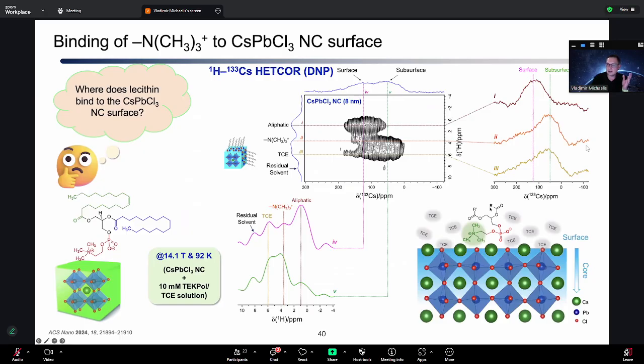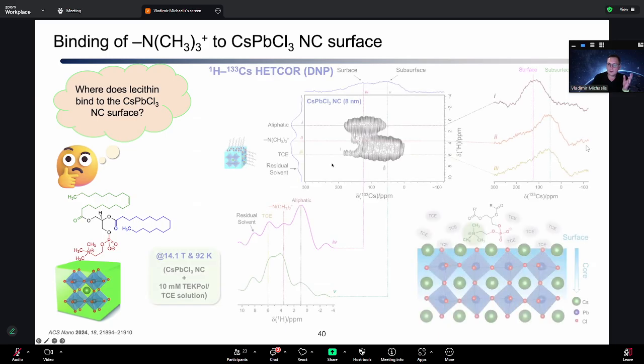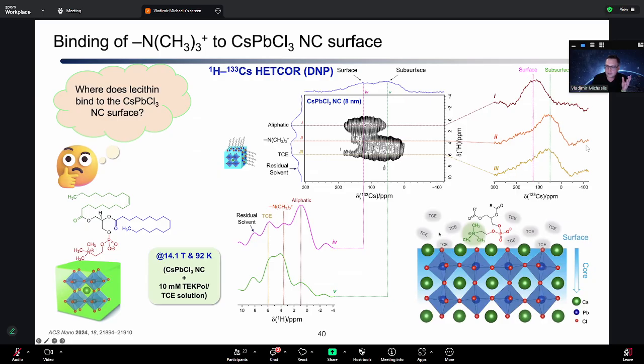So these protons here are seeing just this area here. If you look at the amine group here, this tertiary amine, right? If you look at that group here, that system is showing you the surface, but it's also showing you subsurface. So what it's suggesting is that this system is getting into one of these environments. It's suggesting cesium is getting kicked out. Okay, and that's really important.